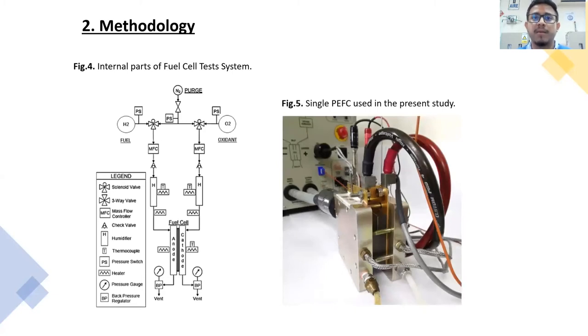The test system comprises volumetric flow controls, heating elements for anode and cathode cells with their corresponding temperature meters, variable DC load, and a frequency response analyzer. The collected data are automatically saved in a computer through the fuel cell software. The main parameters set were a temperature range between 40 degrees Celsius to 90 degrees Celsius, and a fixed current density of 2 amperes per square centimeter, which corresponds to the maximum applied load of the system, that is 50 amperes.